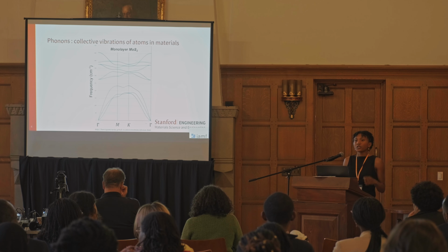We perform another experiment where we keep the laser power low and change the temperature of the stage that our sample is sitting on so that we can correlate the different peak positions to an actual temperature of the material. At the end of the day, what we get is an understanding of how the temperature of the material is changing with different laser power. And we can fit this to a thermal dissipation model where the thermal properties of our material of interest are our best fit parameters. So here what we're interested in is the in-plane and the out-of-plane thermal conductivity.